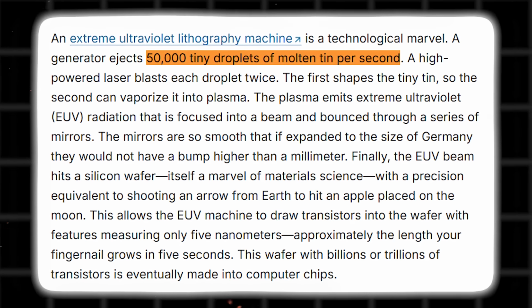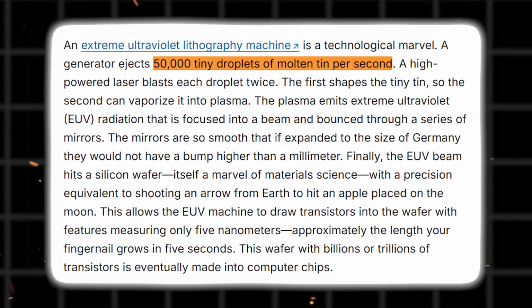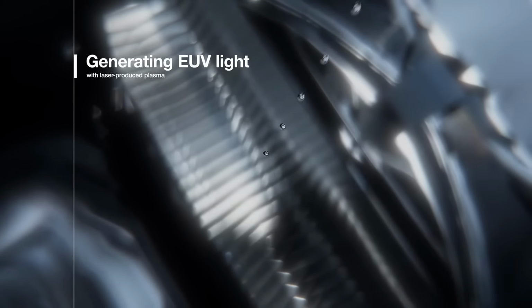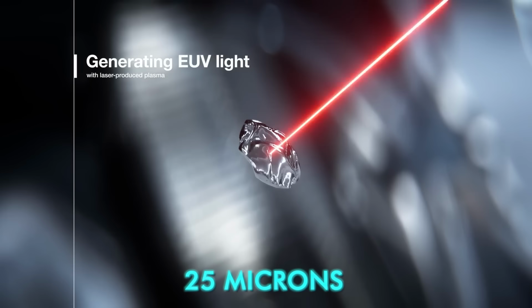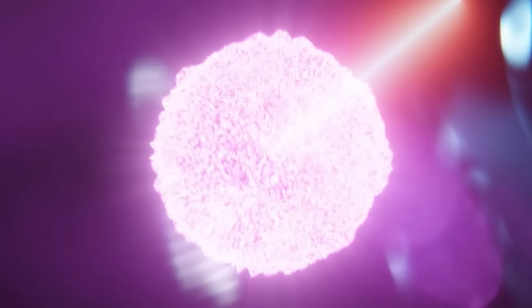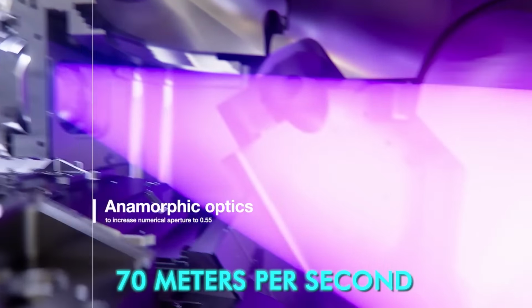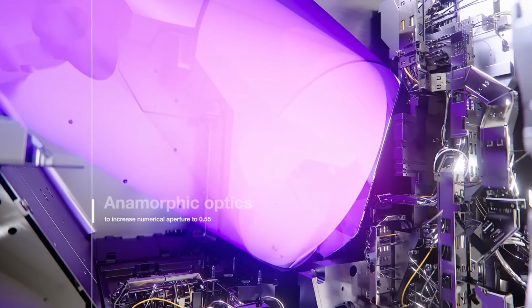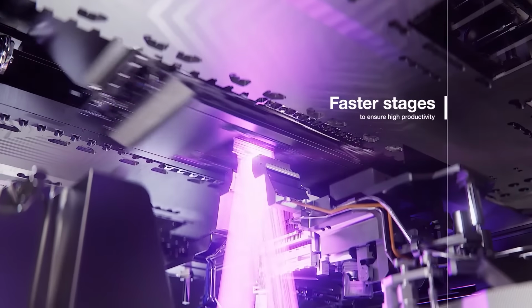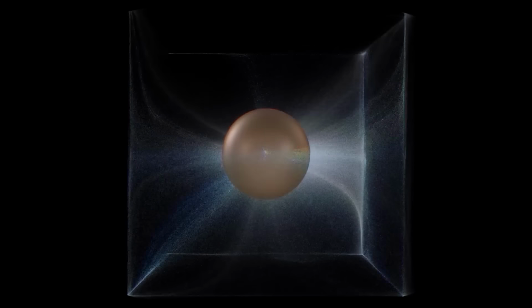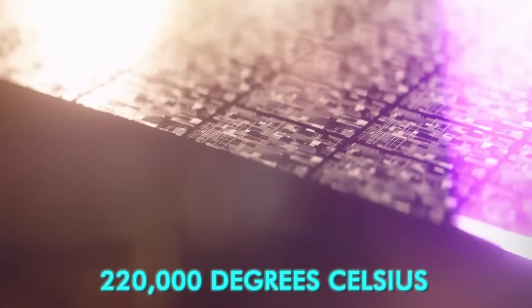Inside the machine, a generator fires 50,000 microscopic droplets of molten tin per second. Each droplet is about 25 microns across, which is roughly a third the width of a human hair, traveling at 70 meters per second. A first, low-power laser pulse hits each droplet and flattens it into a pancake shape. Then a second, far more powerful CO2 laser blasts the pancake and vaporizes it into plasma that reaches temperatures of around 220,000 degrees Celsius, which is roughly 40 times hotter than the surface of the sun. That plasma emits EUV light.